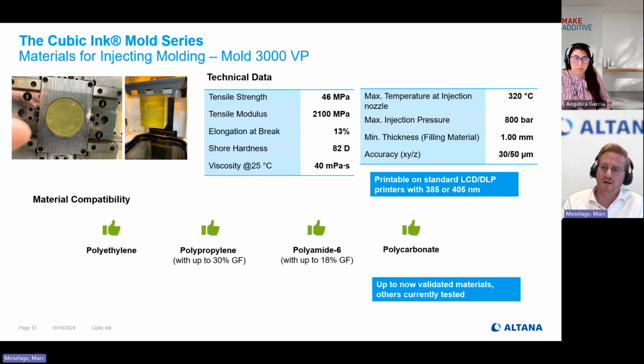Exactly. Also worth mentioning, this is a material for open printers, printable on diverse LCD and DLP printers with the standard wavelengths as indicated. We've also tested this material at a lot of companies we're working with. Polyethylene works well, polypropylene works pretty well, even with a 30% glass fiber filling. Polyamide, this is really the vast majority of the materials printed, really PA6. It works unfilled, but it also works pretty well for PA6 with 18% glass fiber. Polycarbonate is also something that works pretty well. Those are the materials we have validated so far.